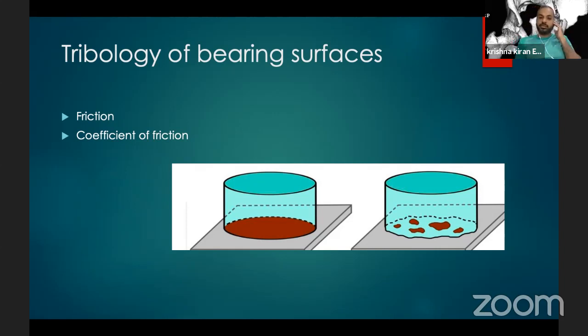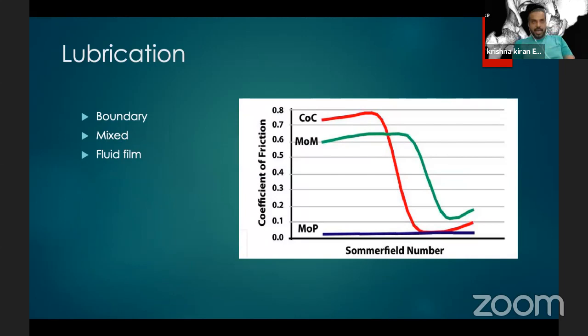Therefore, there can be a higher risk of wear unless there is a fluid film interposed between these opposing surfaces, which is thicker than the highest asperity on each surface. By that, I mean the lambda number. The lambda ratio is the thickness of the fluid film, and it should be greater than 3. That indicates that it is higher than the largest asperity on the opposing surfaces. So if you have a metal femoral head with a 3 micron asperity on its surface peak, which is in contact with the polyethylene, then the surface area is so low that it will remove polyethylene over a period of time. But if you have a fluid film which separates these throughout the swing and stance phases, then the wear rates are lower.